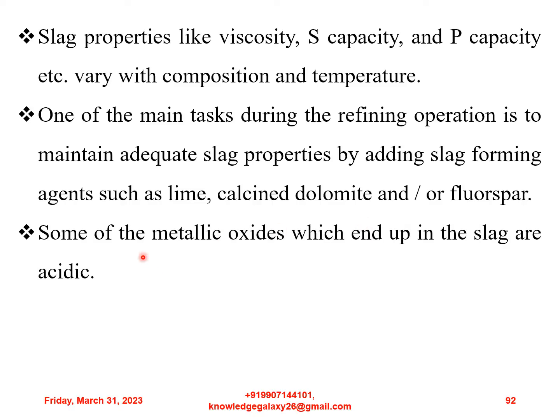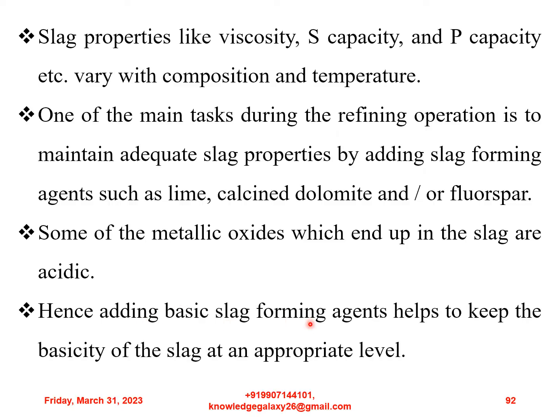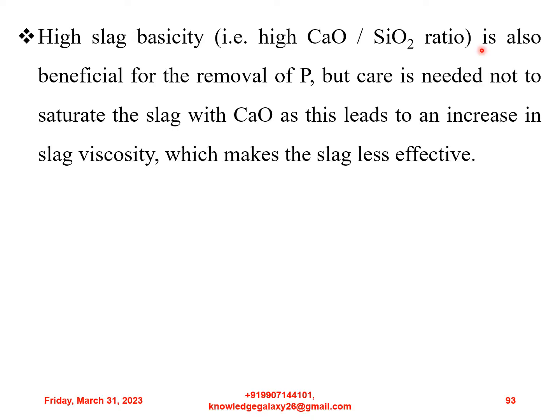Moving on, some of the metallic oxides which end up in the slag are acidic in nature. Hence, adding basic slag forming agents helps to keep the basicity of the slag at an appropriate level. High slag basicity, that is high CaO by SiO2 ratio, is also beneficial for the removal of phosphorus, but care is needed not to saturate the slag with CaO, as this leads to an increase in slag viscosity which makes the slag less effective.